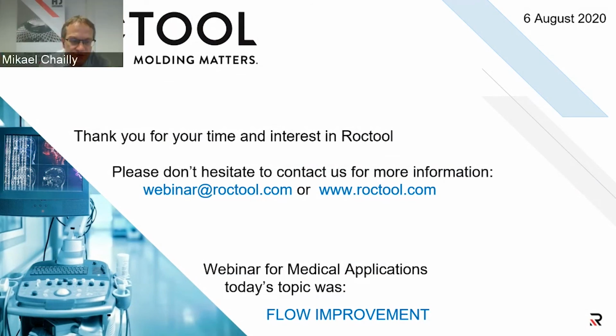If we consider injection, the price in cycle time is very limited, especially since you heat only one side of the mold. As soon as the mold opens, the part stays on the core side and you are heating the cavity side, for instance. You can directly start heating while demolding the previous part, so you finish heating the mold by the time you're ready to close and inject again. This has no impact.